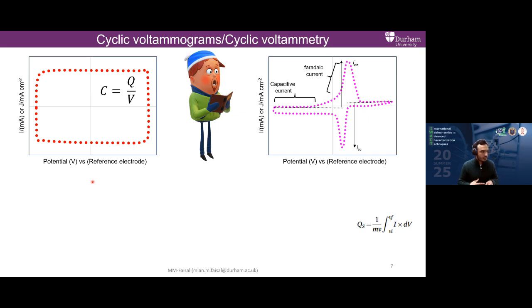So first of all, if you get a rectangular shaped CV out of any material, there are two assumptions. Either your material is purely an electric double layer capacitor, which stores charges through electrostatic accumulation at the electrode and electrolyte interface. Or another assumption is the material can facilitate some redox activity, and that's how it can be categorized as a Faradaic pseudo-capacitive material. So that's the first two pieces of initial information which I can dig out from the cyclic voltammogram behavior. What else can I do?